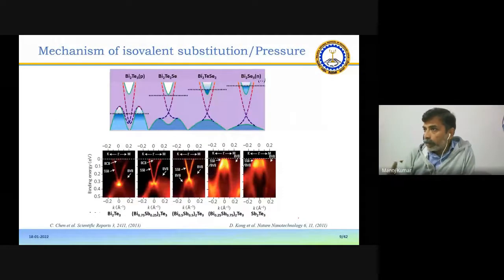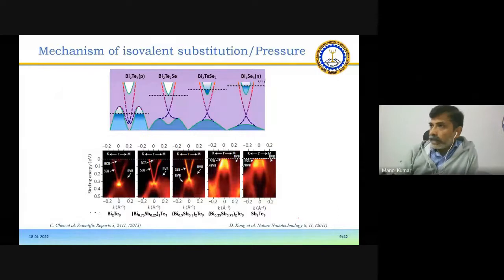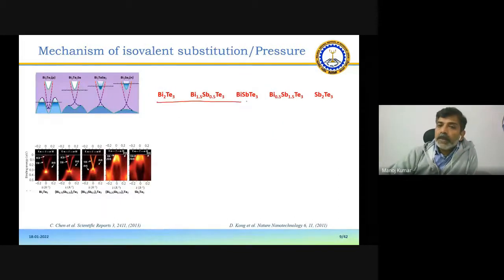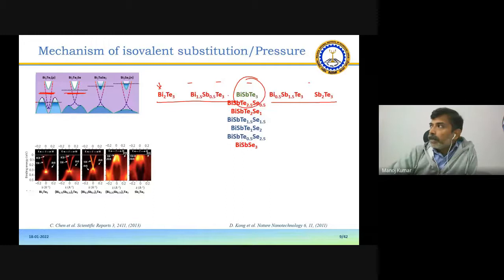It's not all the time necessary that compressing will increase the band gap, but in this material, it is increasing the band gap. So this isovalent substitution, we can first tune this material using one type of replacement, like replacing bismuth with antimony. And we can think of in between somewhere, we can have this Fermi level to be in the middle of the band gap, bulk band gap, to maximize the surface conduction or to minimize the bulk conduction. So we can have somewhere here, we expected that this will be in the gap. And to further optimize the position, we can actually now go in other direction by replacing tellurium with selenium.